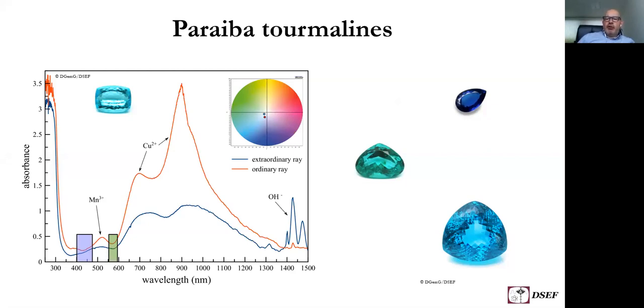However, the first stones that we had in our lab all showed a different color. They actually were sort of a tanzanite blue. And these were unheated stones. All these stones we had in our laboratory, we certified them. This stone has a weight of about 5 carat. This is from Batalha. This stone had a weight of 12 carat from Batalha. And this is an exceptional stone, also from the Brazilian deposit, of more than 65 carat. So these are unique specimens for Brazilian Paraiba tourmalines. Normally, Paraiba tourmalines from Brazil are less than 1 carat.